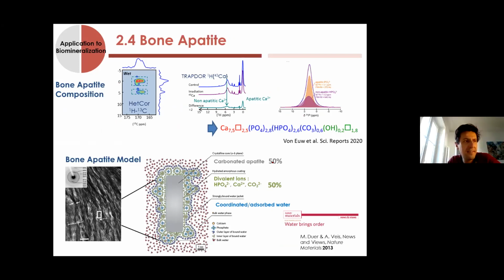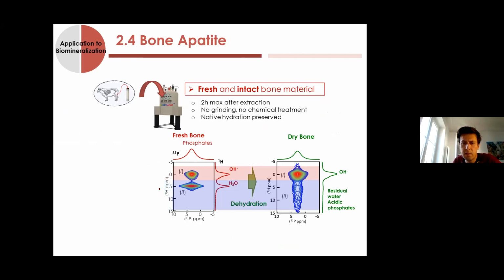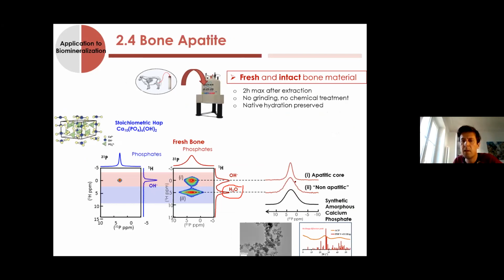Yes, that's an excellent remark. Of course we had that problem in mind, but I would say in that case I'm more thinking about 2 different independent domains, because when you are looking at that specific signal, and you are looking at the exchange between these 2 signals with the specific experiment that I showed you before - if you have a gradient, you should see a specific gradation of the signal, starting from something thin and going to something broad. And actually, you don't see that. You see really a transformation of something very thin into something very strong, very broad.